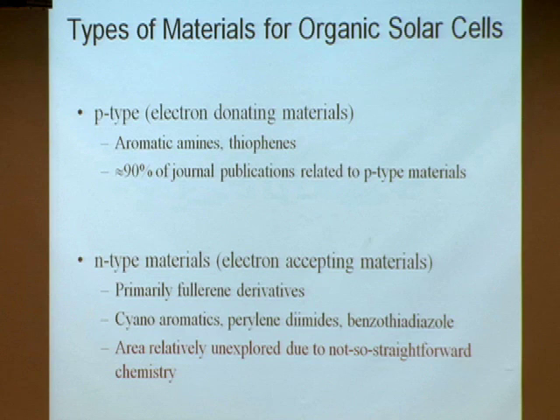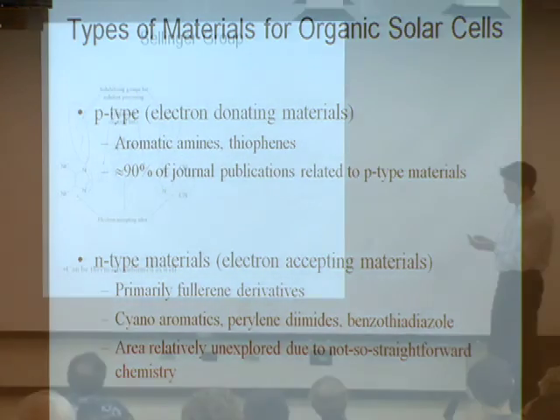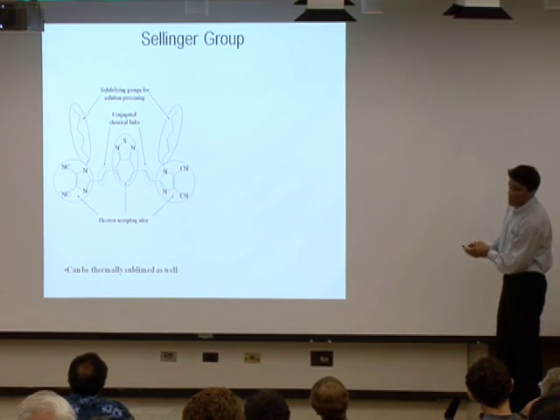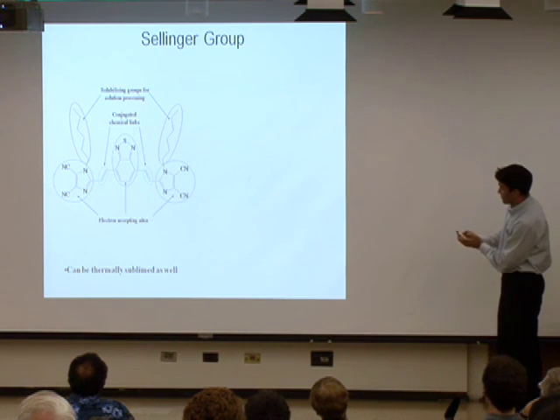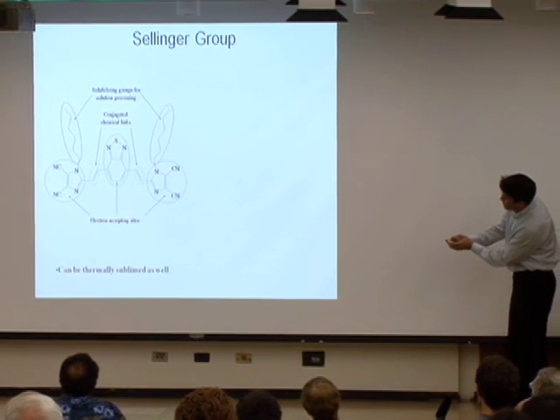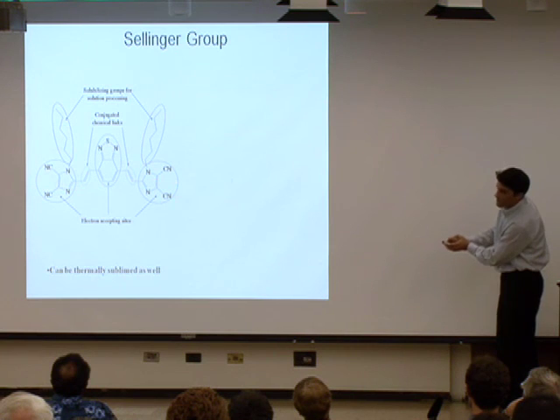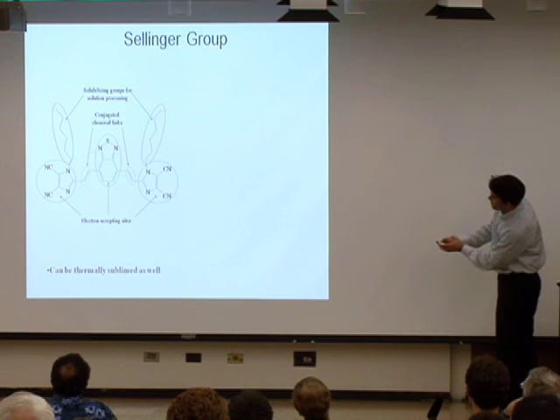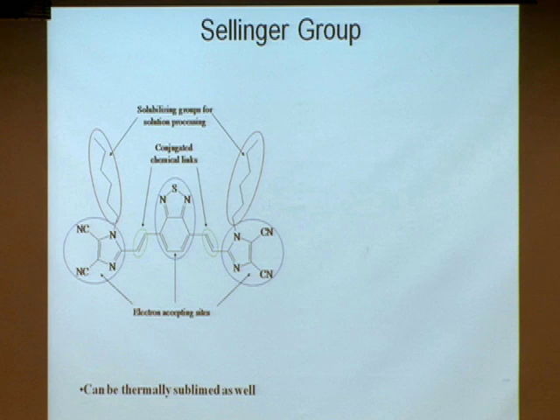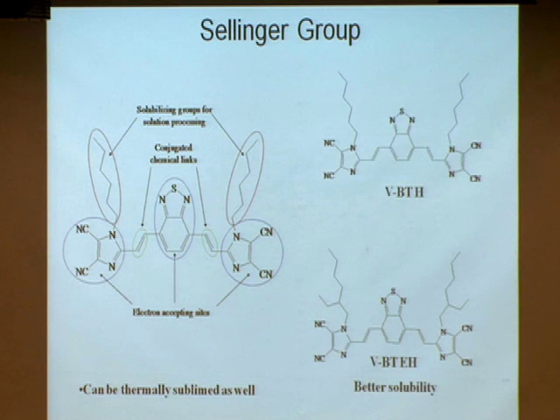And so here I'm just briefly showing some of the design and strategy for a particular molecule. Here we have a system that is very electron deficient, so that means it can accept electrons. These electrons can be delocalized within the molecule because we have introduced these vinyl groups which allow electrons to move within the molecule. We also have these groups on the side that Mike mentioned can be used for solubility. So in this case, we can use this in solution processing if we make these quite large, or if we make these small, we can actually sublime these and use them in small molecule solar cells. So they're fairly versatile, and here, just showing that in one case we have a 6 carbon chain, and if we add a 2 carbon chain off to the side, it turns out that that's much more soluble and can be used in other types of systems.